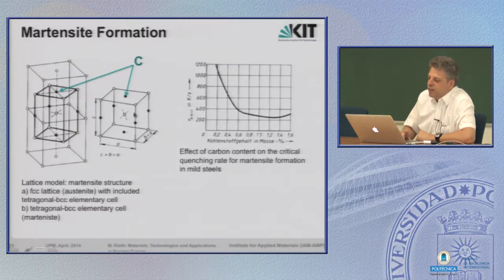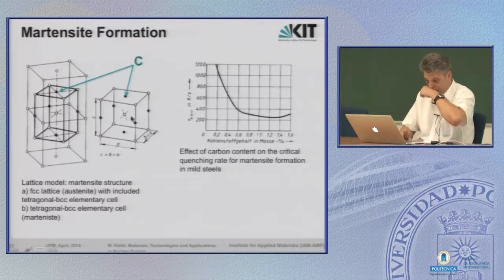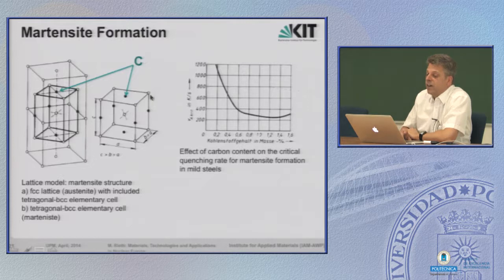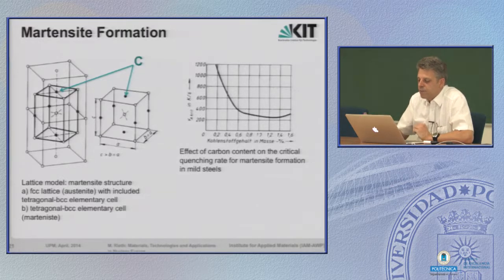In principle, it's a BCC structure. On each corner, we have an iron atom. In the middle of this structure, we also have an iron atom. That's a body-centered structure. But the structure is not equal on all sides. It's a bit distorted along one axis. So that's what we call a tetragonally distorted BCC elementary cell. And that's the martensite lattice structure.